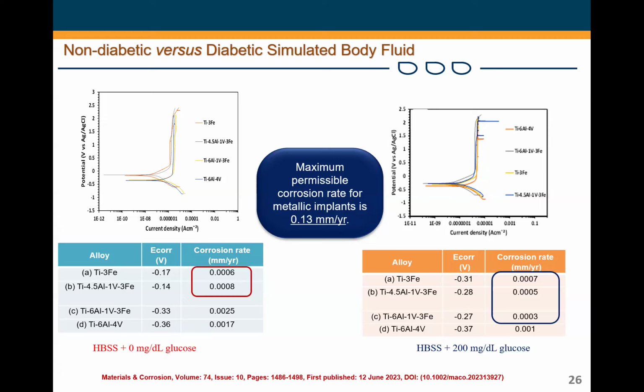And this seemed to be a very, very positive result for us, knowing fully well that if you start having a very high rate of corrosion, that could be detrimental to the human body. So again, from a corrosion standpoint in physiological environment in glucose, we were quite happy with the result that we got. So iron does not only improve maybe strength and ductility, especially when you have a situation where the substitution is partial, it's not total, right? So iron also has a way of helping to slow down the corrosion in extremely acidic environment. But in terms of physiological solution, it's just happy.